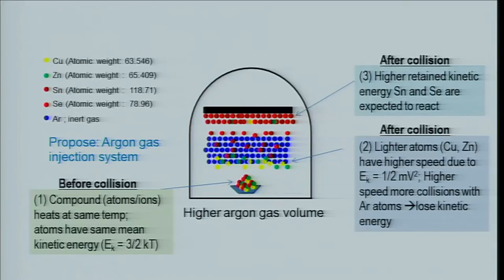During the formation of the film, which was in vacuum, if we can control the number of atoms that go up to form the thin film, for example, if we have copper tin selenide, we let the tin selenide go up, and we try to limit the amount of copper that goes into the thin film. To do that, we hypothesize that if we allow a gas in between the substrate and the source, and we can regulate the amount of gas in between, the atoms that go up will make collisions, and from there we can optimize the condition such that only the atoms that we want will be able to go through. So that is the short story.